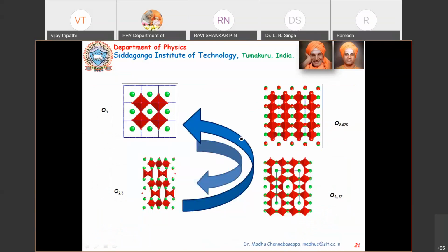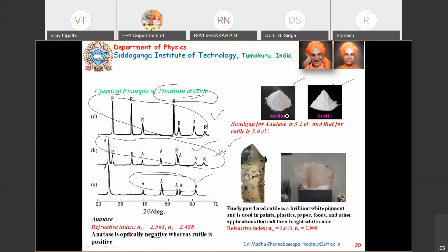This is from my work. We have done some work on this. This is your SrFeO3, and based on the oxygen stoichiometry, you can have different kinds of materials. In this case, for example, if you take anatase and rutile, anatase is the low temperature phase, or it is at low thermal equilibrium. If you go to higher temperature, anatase is going to get converted to rutile. For example, if you take your anatase powder and start heating at 600, 700, 800, after 800 it will become rutile, and this is irreversible. You cannot bring rutile back into anatase. So this is an irreversible process.